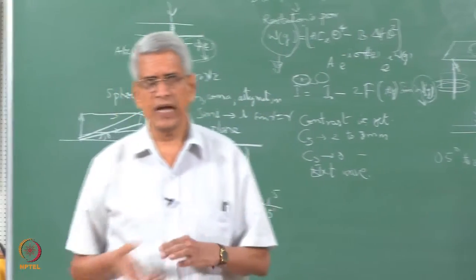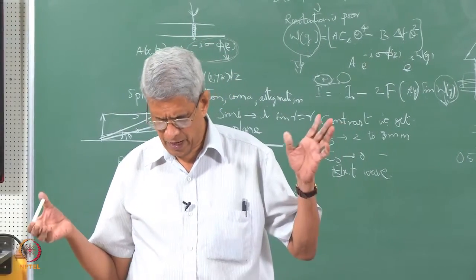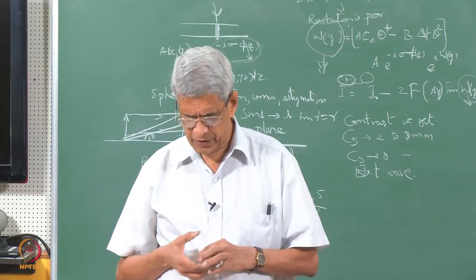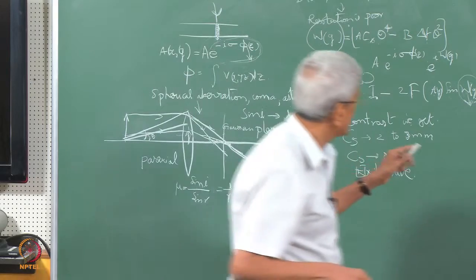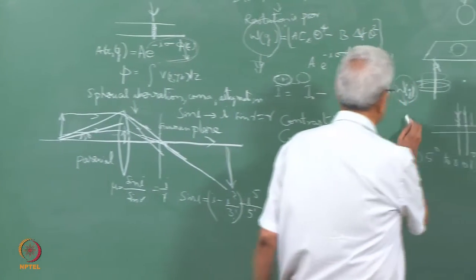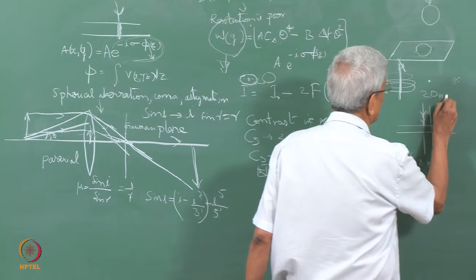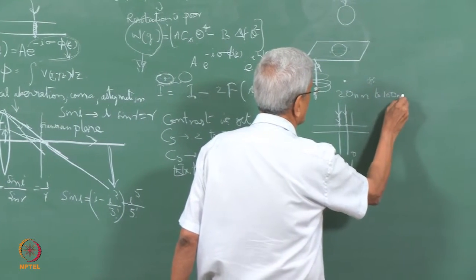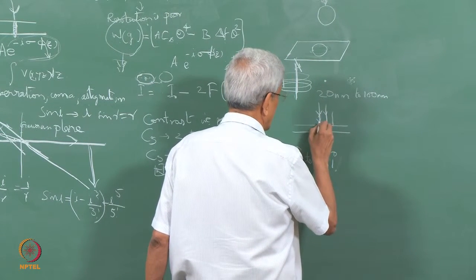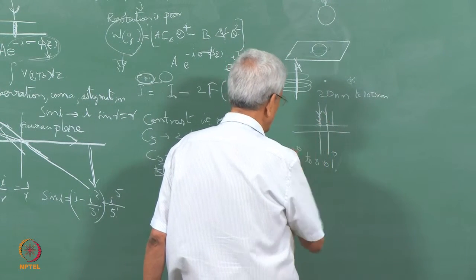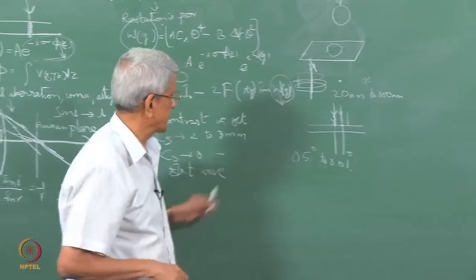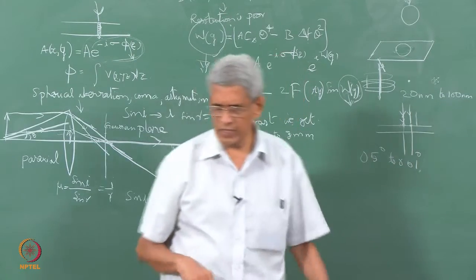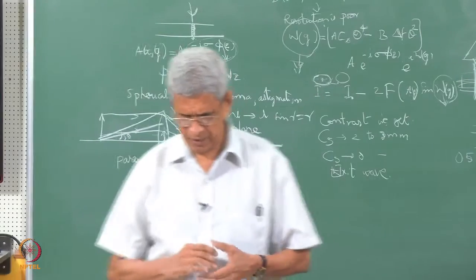The area which we scan could be some micrometer square to millimeter square, and the lateral resolution, the beam size, could be from 20 nanometer to 100 nanometer. With this resolution, we can get information from region to region. A small misorientation of about 0.5 degrees could be easily measured.